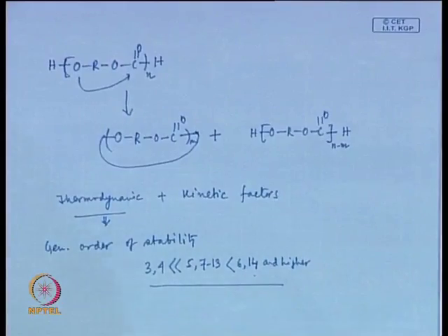Now, I was saying that if you have larger linear molecules, say having 14 or higher number of atoms, then they have so many conformations. The longer the chain, the more conformations of that molecule are possible. And so, the probability that any conformation will have these two reactive functional groups coming close to each other, so that they can react and form a ring, is always very low.